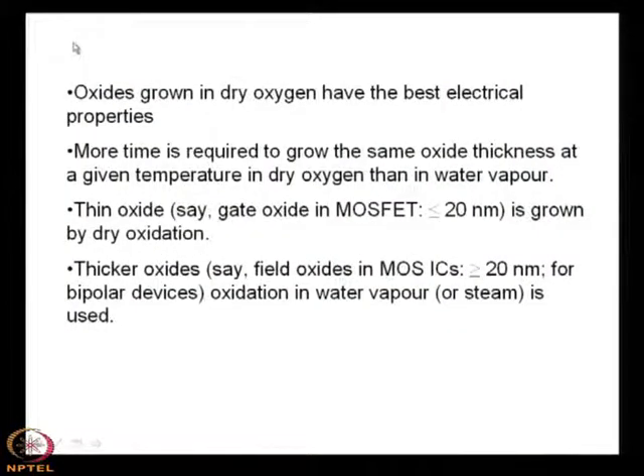Now, some comments about the thermal oxidation: the oxides grown in dry oxygen have the best electrical properties. More time is required to grow the same oxide thickness at a given temperature in dry oxygen than in water vapor. So, that means dry oxidation is a very slow process, and if you want to grow say 50 nanometer or 20 nanometer oxide layer by dry oxygen, if the time required using dry oxidation is T1 and that using water vapor is T2, the same thickness, say x nanometer,